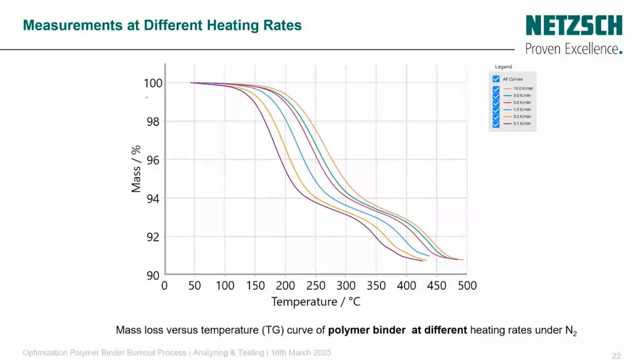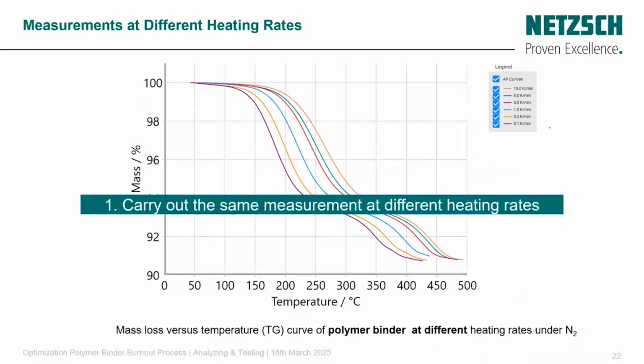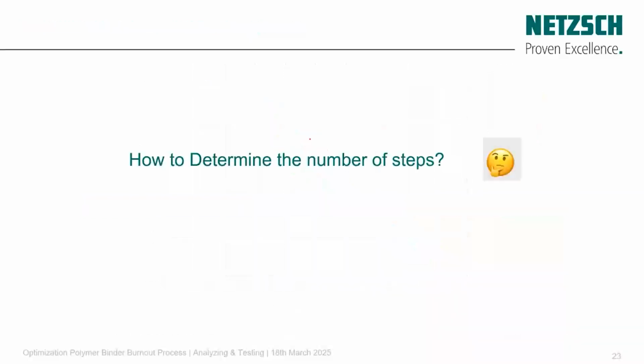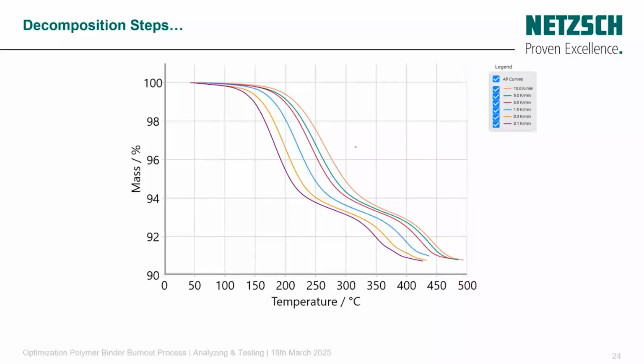So here we made the measurement at different heating rates, basically 6 heating rates. As you can see, 0.1, 0.3, 1, 3, 5, and 10 K per minute. And then one of the crucial steps is how to determine the number of steps. The easiest way is by visual inspection of the curves, where we can see clearly that we have 2 steps. But if the TGA curves show more than one inflection point, looking like an overlapping of 2 or more S-shaped curves, the process is certainly not only a single step or just 2 steps. So that's why we need another tool in order to get the confirmation, to be sure that we have only 2 steps.